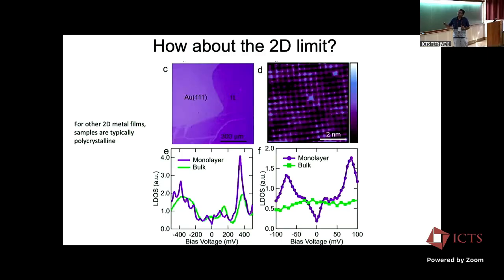But if you look at 2D metal films where signatures of weak localization and so on have been seen, these have all been sort of polycrystal or amorphous materials. Here is an example where we can take this material, we can just use Scotch tape exfoliation, and we can go down to 1 layer in thickness. But now, because it's exfoliatable, because we can go down and really measure this, we can really measure not only transport properties, but we can also measure spectroscopic properties in this 2-dimensional limit. And we see something quite interesting. It's something that we still haven't digested yet. It will appear in PRL without much explanation.